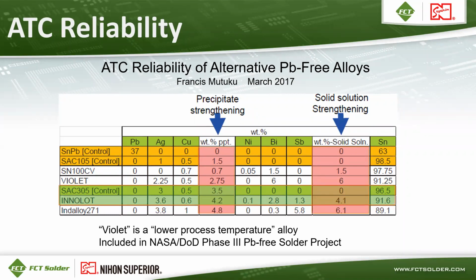Violet's a lower process temperature alloy that is being tested by NASA and the Department of Defense in a lead-free solder project. Now there's two highlighted columns. The first one is precipitate strengthening, and that's the concentration of elements in the alloy that will form precipitates, like Ag3Sn, Cu6Sn5, those sorts of precipitates. And those will coarsen over time, and those will lose effectiveness over time.